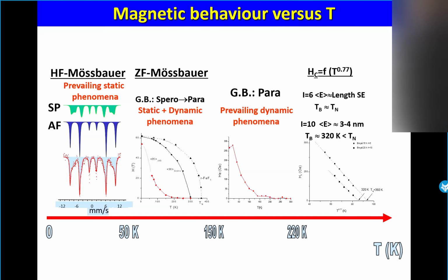And by considering here the evolution of the coercive field, you can estimate the blocking temperature. When the grain boundaries are very thin, you have a blocking temperature equivalent to the Néel temperature. That means you have no strong dynamics. But when the grain boundaries are rather thick, of course, you are preventing interaction between grains. That means you have a blocking temperature which is lower than the Néel temperature.